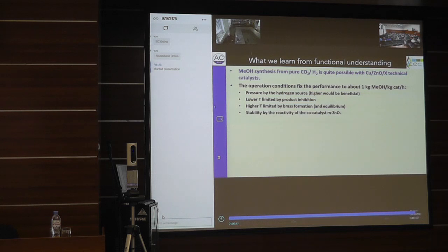And the stability of the whole system is given by the stability of the co-catalyst zinc oxide. If the zinc oxide is recrystallizing and cannot dynamically respond to the surface change of the copper anymore because it's a thick crystal, then the catalyst is also dead. So we know now exactly what are the ingredients that allow the catalyst to operate. The active sites are located in the perimeter between the two co-catalysts, between oxygen-containing copper metal and zinc oxide that has defects. And however you make this perimeter, this depends on your choice.